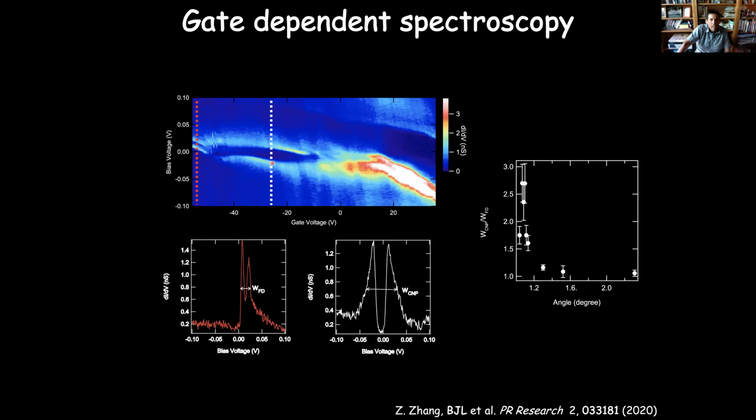And this corresponds to the charge neutrality point. At the charge neutrality point, we have exactly filled one band on the left, and we have a second band which is completely empty. As we've gone from fully depleted to charge neutrality, the interactions have pushed these bands apart and opened a gap of something on the order of 25 or 30 meV between them.